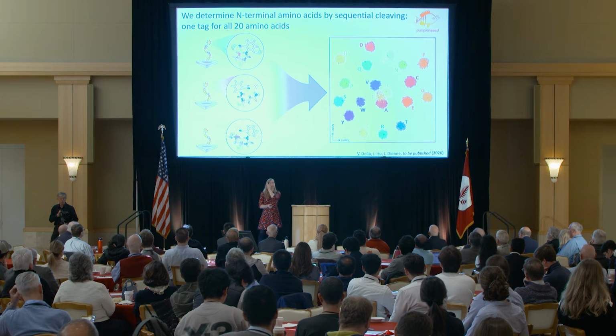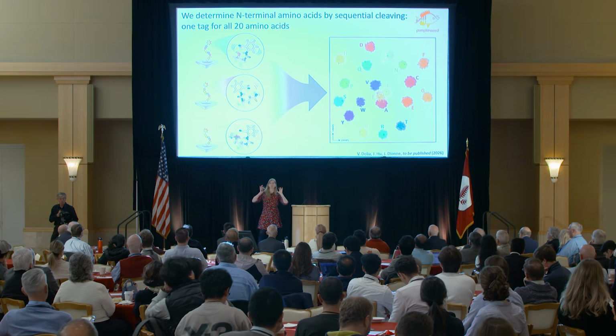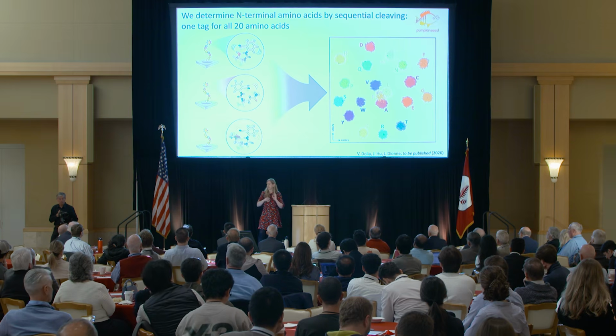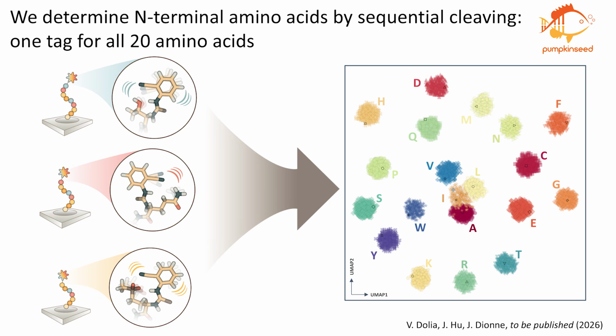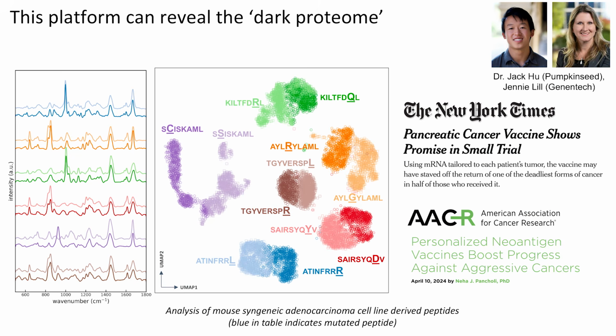And here, for one Edman reagent, I'm taking the Raman spectra of a peptide with different terminal amino acids, shown here, and then projecting that spectra onto a two-dimensional plane. You can think about this as a PCA, but it's basically a UMAP in this case. And then with the spin-out company, Pumpkin Seed, one of the founders and my former student, Jack Hu, has been working very closely with Genentech, where they're interested in using this platform to reveal what broadly would be called the dark proteome.